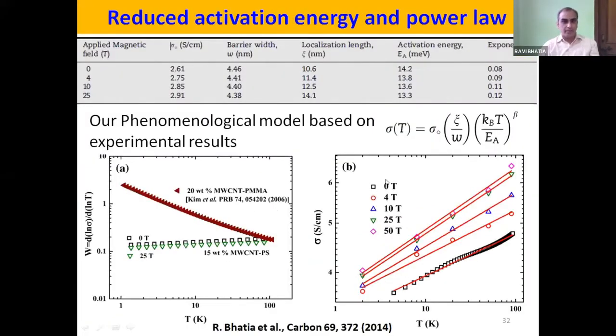Here I will again explain the WT graph of the 20% sample of PRB. You see the W increases with the decrease in temperature for a sample of 20%. That shows that it is in the insulating regime. However, for our sample, the conductivity lies in the metal insulator boundary, or one can say it is a critical regime.